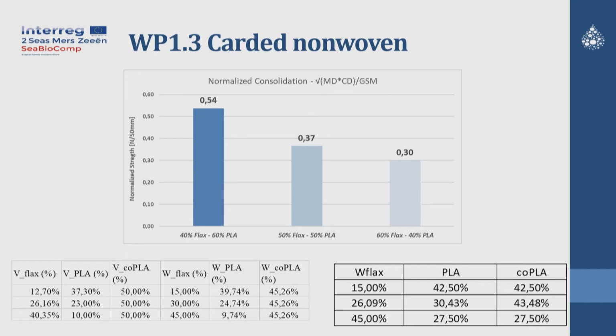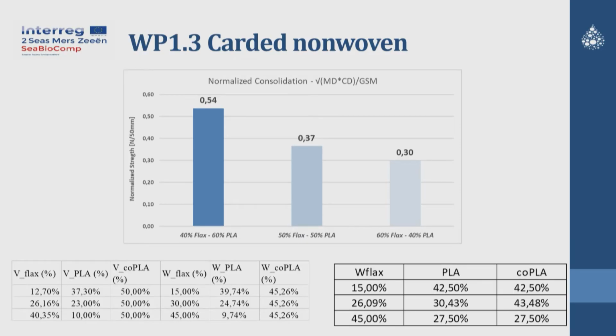It's also the normalized strength here, and we clearly see that a good ratio of fiber is 60% PLA and 40% flax. But with the results that we have developed with ARMINES, we have seen that we have to add other components, such as low melt composition, which could play a role in elongation. So ARMINES try to add some low melt fiber, low melt components, to add elongation without disturbing the tensile strength in composites. Here it's always on textile. That's why you have this table, to manage the good ratio of fibers and flax.